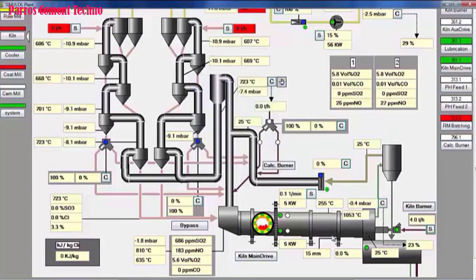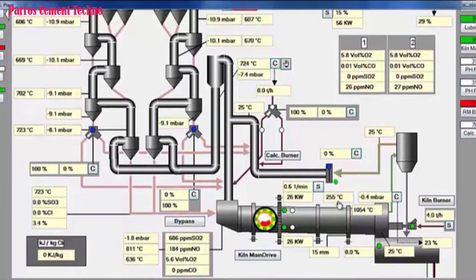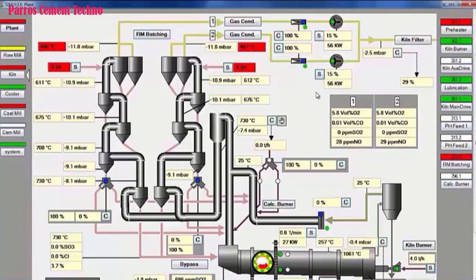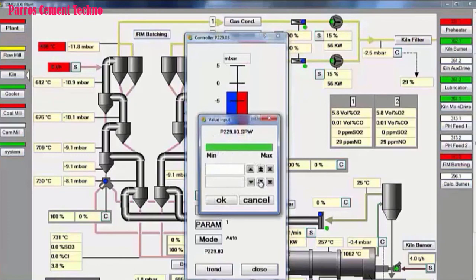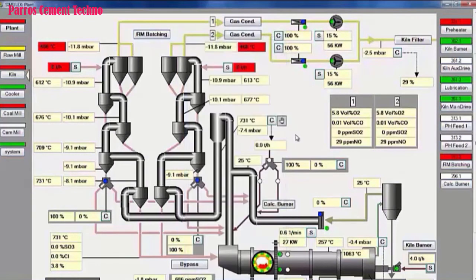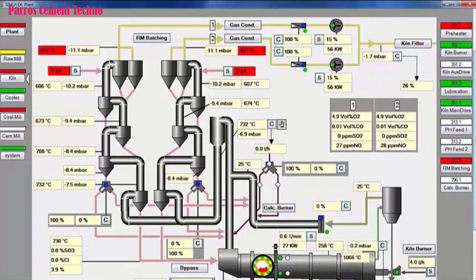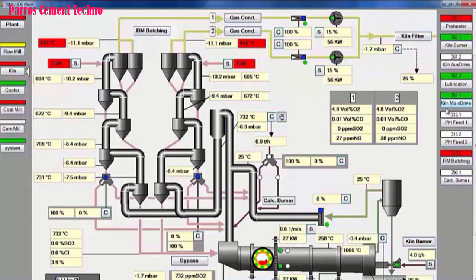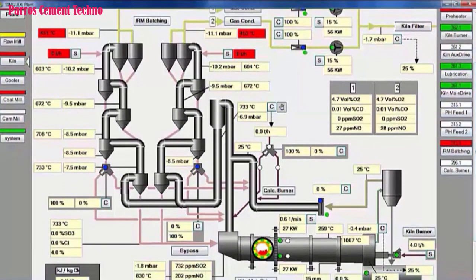Kiln shell temperature is 256 degrees Celsius, and this kiln migration is 15 mm. For normal kiln operation the migration is usually 10 to 15 mm. Then the kiln inlet temperature is above 800 degrees Celsius. And the temperature at the top of the preheater is very high. This must be attempted to decrease by reducing the draft behind the preheater setting from -2.5 mbar to -1.5 mbar. We can prove that by reducing the draft behind the preheater ID fan, the top temperature of the preheater decreases slightly. Because all control parameters and all temperatures in the preheater, sintering zone temperature, kiln inlet temperature, and kiln main drive have been run, then the kiln is ready to start feeding.